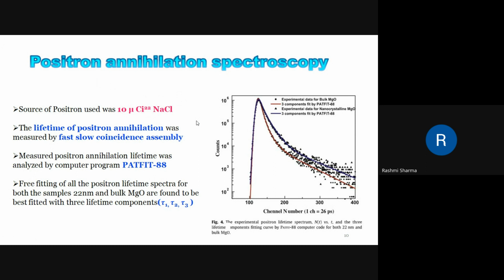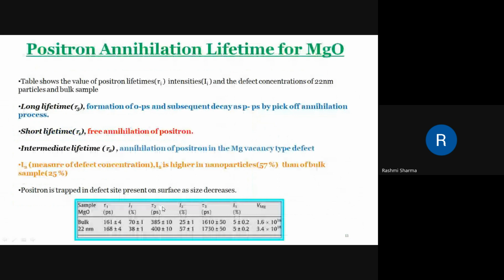The positron annihilation lifetime was measured by a fast-slow coincidence assembly, and this measured lifetime was analyzed by the computer program PATFIT88. Three lifetime components are used: tau 1, tau 2, and tau 3. In this table, tau 1, tau 2, and tau 3 are the lifetimes of the positron, and I1, I2, and I3 are their corresponding intensities. The lifetime tau 3 is longer as compared to the others.